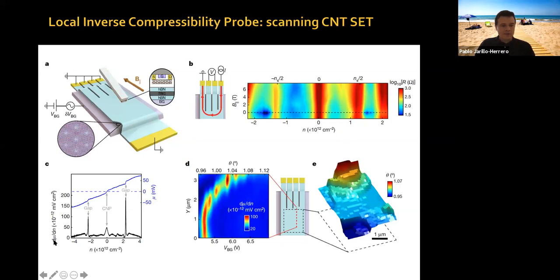This is a measurement of the dμ/dn, this black trace. As I told you in the early phenomenology, gaps appear as these sharp peaks. The charge neutrality point, the Dirac cone, appears also as a peak because of low density of states, so large inverse compressibility, and it decays in a special way. You can see extra wiggles. We're going to see those extra wiggles in a moment. If you integrate this inverse compressibility, you get the actual chemical potential of the system as a function of density, and you can see steps in chemical potential at each of these features.